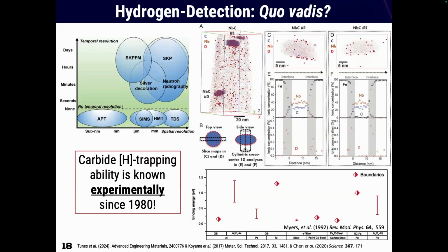The limitation of hydrogen detection in materials science is here. We have only one technique that is capable of detecting hydrogen at sub-nanometer scale, which I call nanoatomic scale, and it's APT. And if you go to the literature to see what people do with APT, they actually do not measure hydrogen directly, they measure deuterium, because hydrogen contamination is quite significant for these guys. And they basically measure the trapping ability of some precipitates.